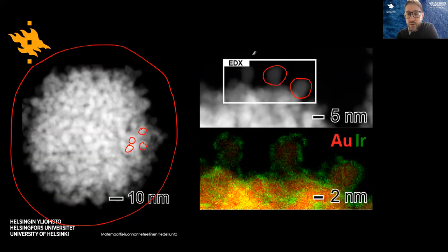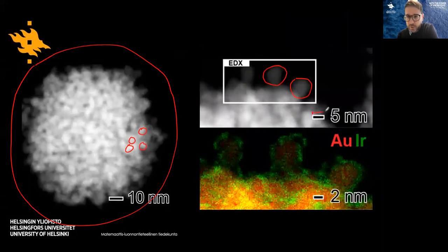So this is an electron microscopy image of these samples, and you can see on the scale bar, this corresponds to 5 nanometers. So each one of these islands is around 5 nanometers in this direction and a little bigger in this direction. So the idea here is that this nanostructure is a hybrid material. These individual branches or islands that comprise this nanoflower structure are composed of gold in the interior and a thin layer of iridium oxide on the surface.